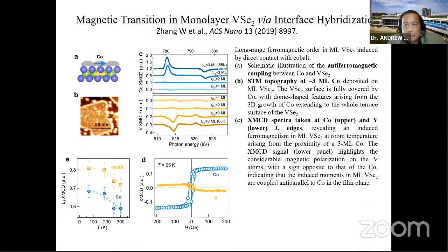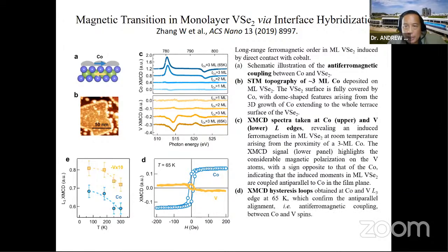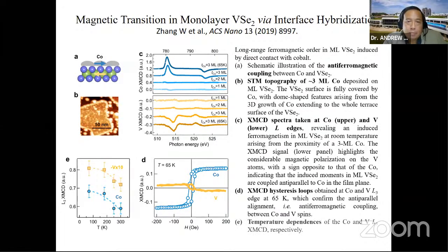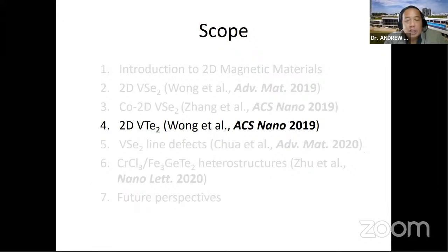Yes, I've mentioned all that. So this paper in ACS Nano in 2019 essentially confirms that we can make 2D vanadium diselenide magnetic if we antiferromagnetically couple it with some magnetic material, in this case, cobalt, right? And we have further evidence that it is intrinsically not magnetic when we studied the other vanadium dichalcogenides like vanadium ditelluride.